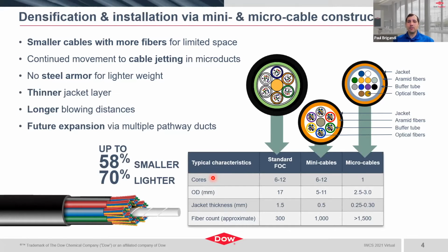We're really looking at moving from the standard fiber cables with the thicker wall jackets and 300 fiber count or so cables, loose tube, to these mini and even micro cables where diameters have now shrunk down to less than 3 millimeters, jacket thicknesses going from 1.5 millimeters down to 0.25 to 0.3 millimeters, and ever increasing fiber counts, as well as number of cables being installed in an existing duct, or future pathways, right? More cables in new ducts.